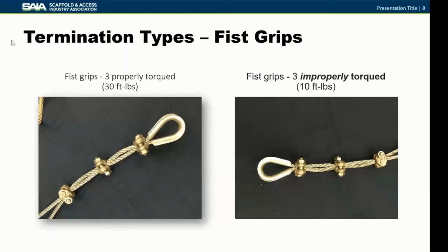We did fist grips, and we used the standard 3 fist grips that were basically spaced about 3 inches apart, and those were properly torqued. It says here 30 foot-pounds. I think the actual torque that's specified is actually 35 foot-pounds. And just to understand what the impact of properly torquing fist grips would be, we also conducted the test with the fist grips improperly torqued, using only 10 foot-pounds of torque on the fasteners on the fist grips.